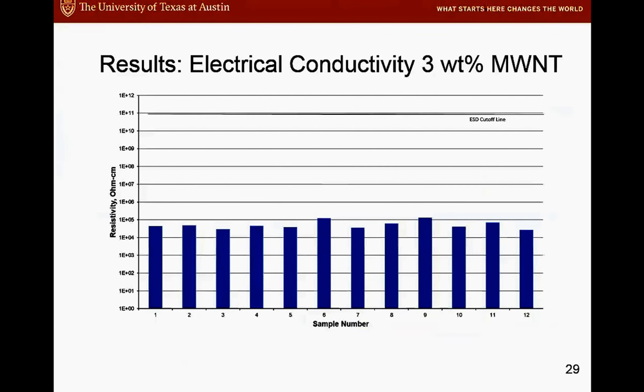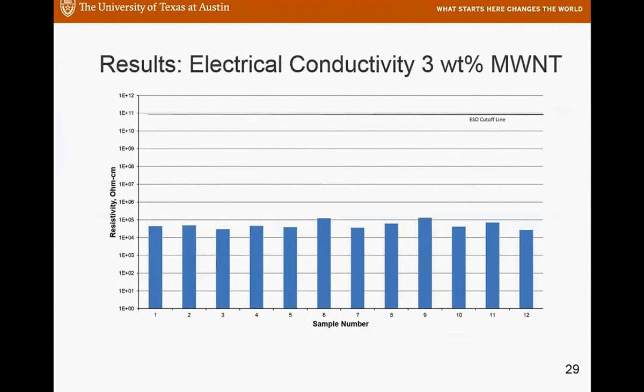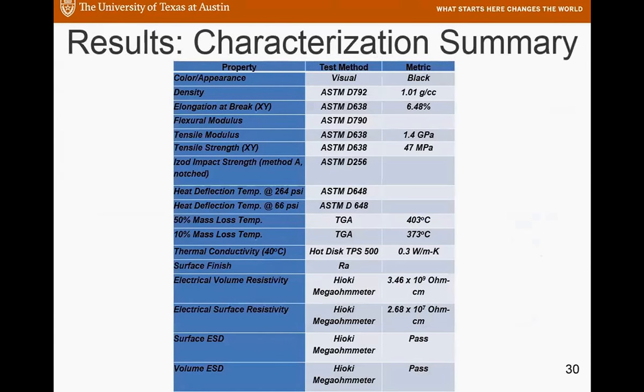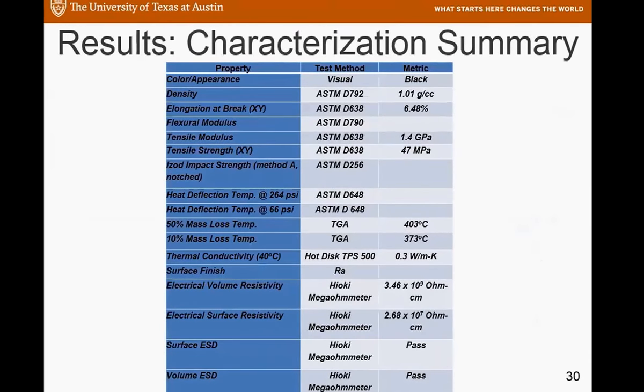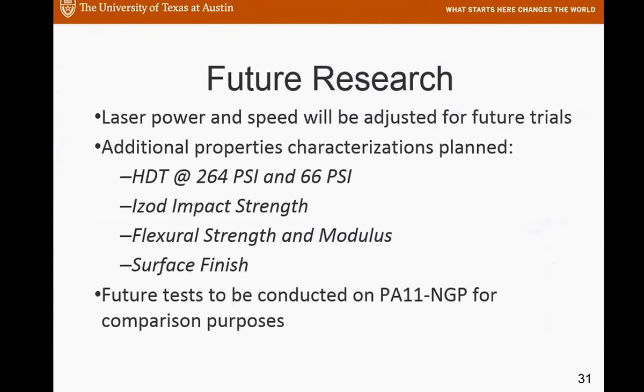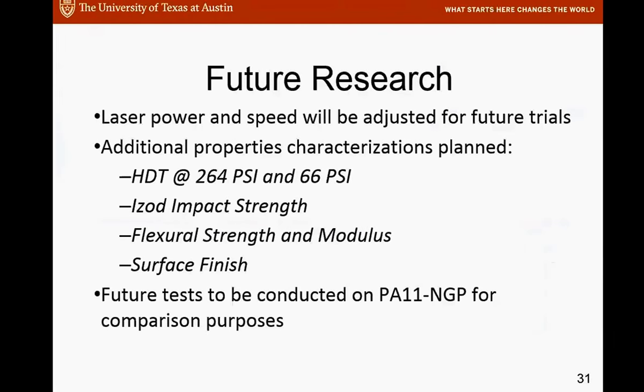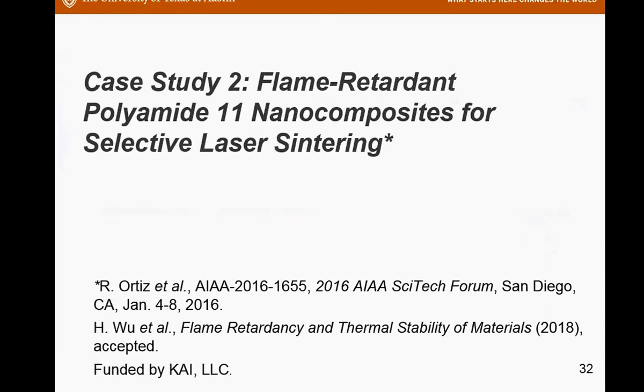And the important thing is, every one of those met ESD, electrostatic dissipation, and we're using a few percent. If you look at the literature, just using carbon fibers, you may have to go 20%. Okay? So we were able to do all that, and this is what I call a technical data sheet. And that's what we fill all these up, and eventually that will be something that you approach a company with, saying we have this, these are all SOS, okay? And these are things that we are finishing up for this particular project, okay?